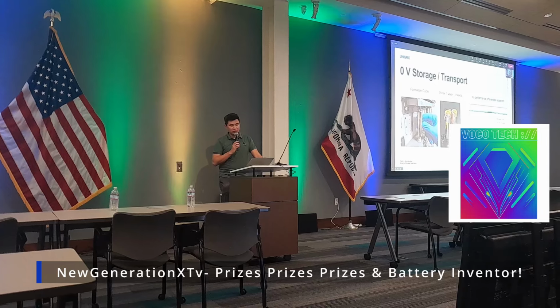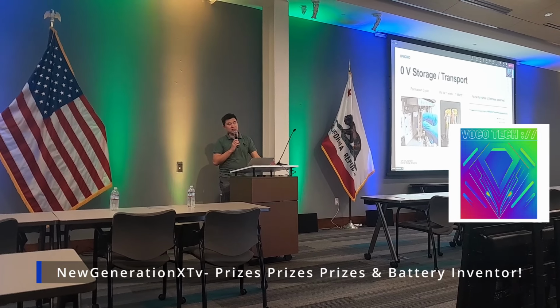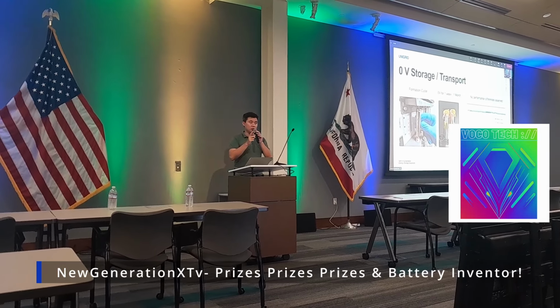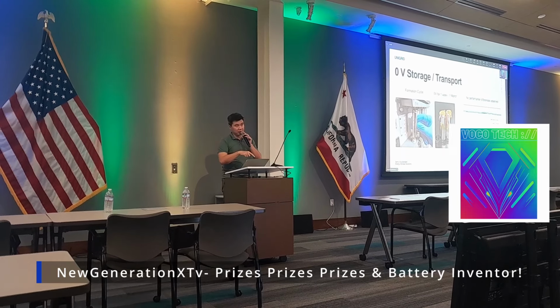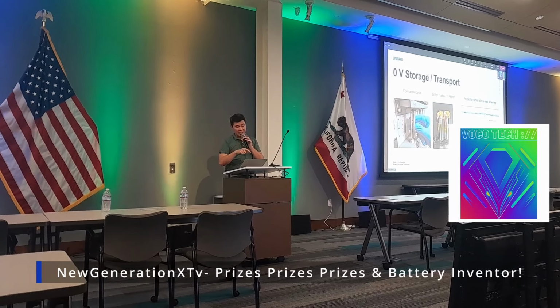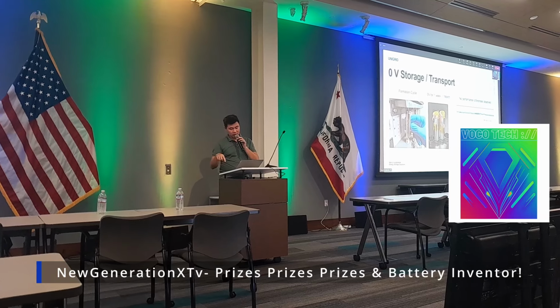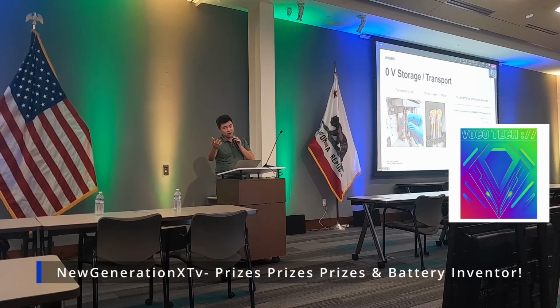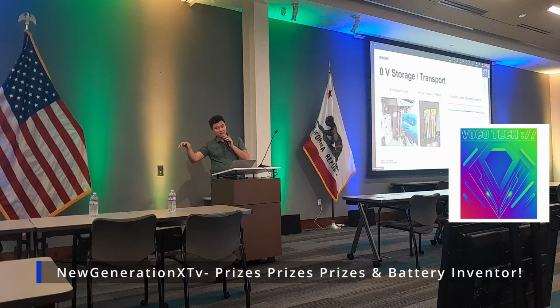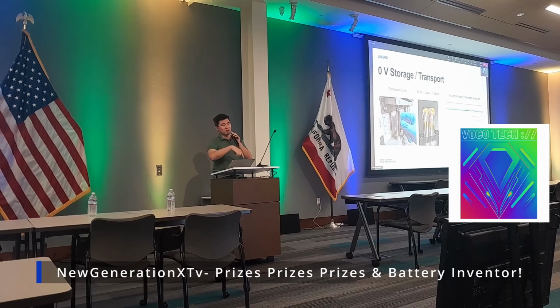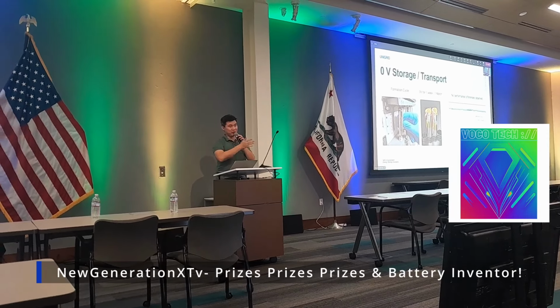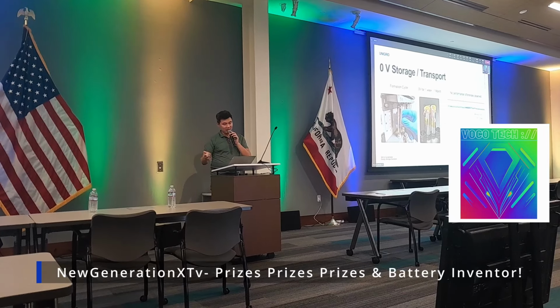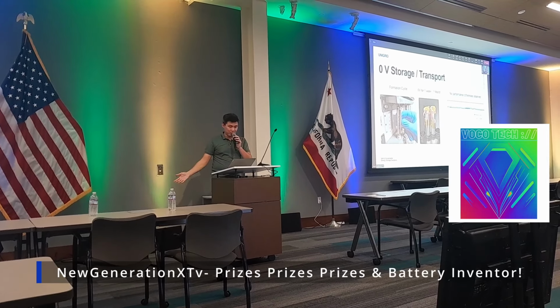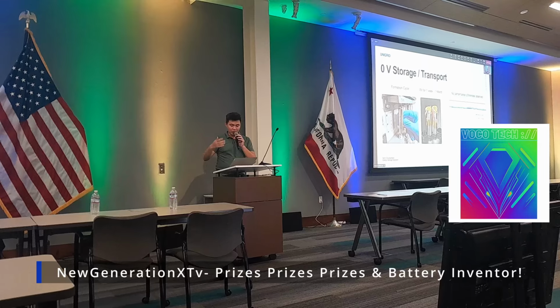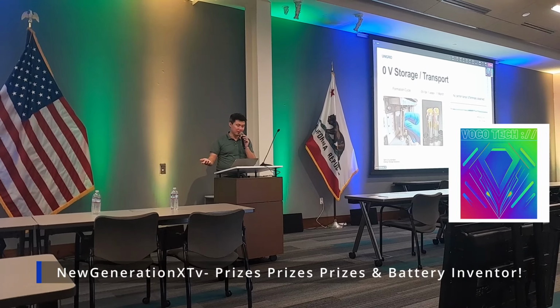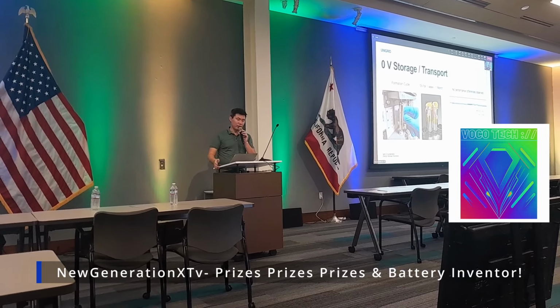No problem. Yeah, the fundamental reason why that is the case is because in a lithium-ion battery, you use copper current collectors on the anode, and copper is really bad for low voltage problems because copper dissolves in your electrolyte solution and it starts poisoning your electrodes. But in a sodium-ion battery, you use aluminum on both sides of the current collector. So you don't have any of these problems. So you can over-discharge it whenever you like, and it's not going to do anything bad to itself.